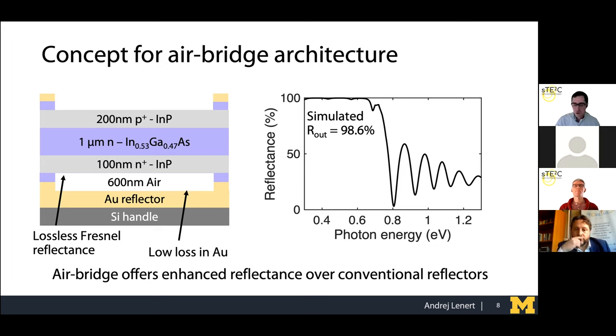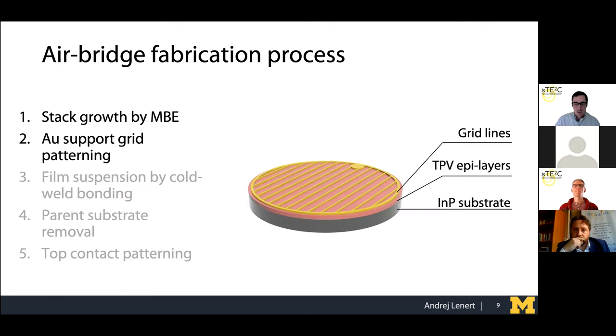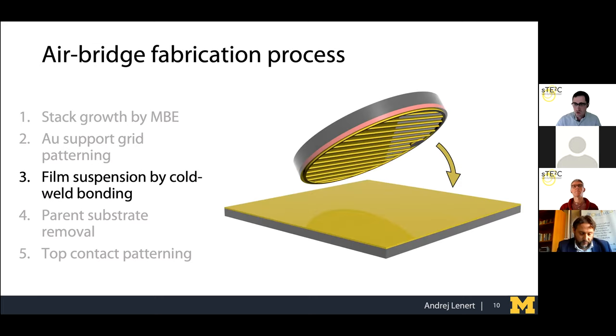So how did we go about making this structure? It ended up being quite simple. It actually eliminated one of the steps compared to our dielectric spacer structure. So we start out with an epi film on an indium phosphide substrate. The epi is the indium gallium arsenide absorber. We put down these grid lines of gold that are about a few microns thick. Then we do a wafer bonding step where we transfer this whole wafer and bond it to a gold coated silicon substrate. So basically a gold mirror. And we do a gold-gold bond at around 150 Celsius for a few hours.